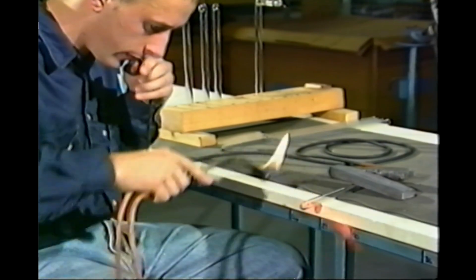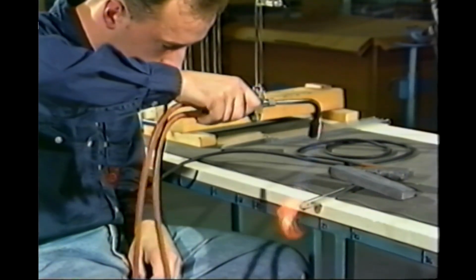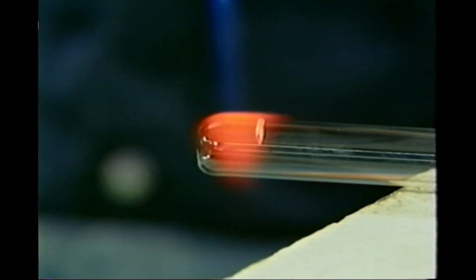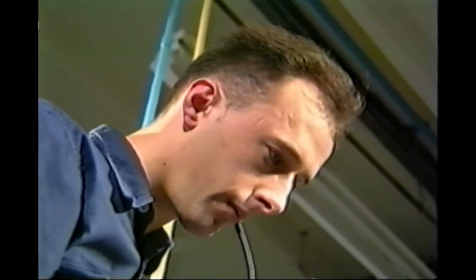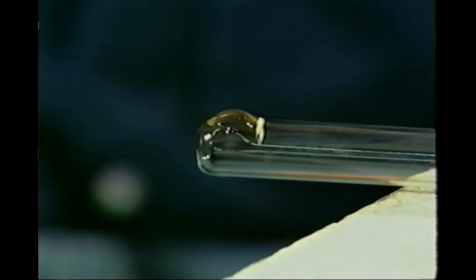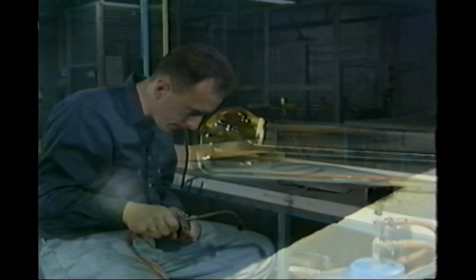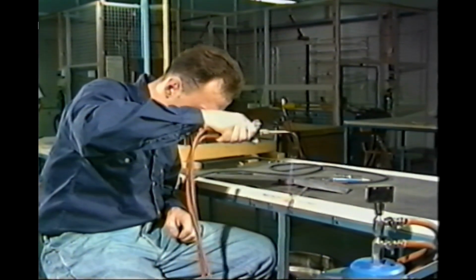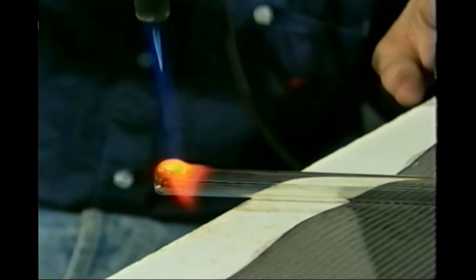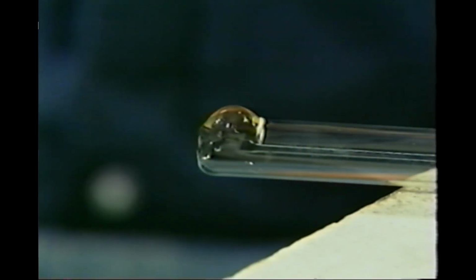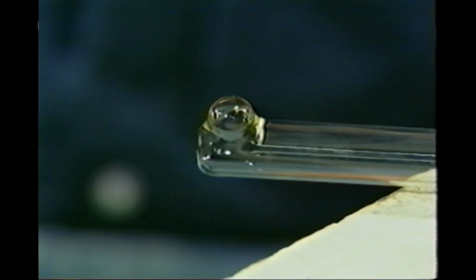To form the electrode joint hole, again using the small sharp flame, point the flame directly down to melt between the butt end and the second pencil mark. Allow the glass to melt down slightly, remove the flame, and blow into the tube to produce a 15 mm diameter bubble. Increase the gas content of the flame, making it bigger and softer. Melt the glass of the bubble halfway down its height. Remove the flame and blow the glass up into another bubble.